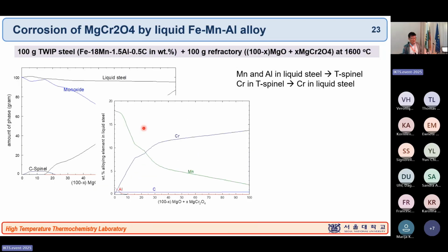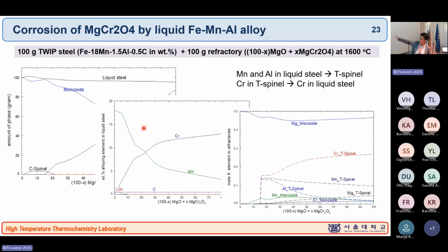But if you look inside the liquid metal, you can see a huge amount of chromium pickup, and this is coming from the MgCr2O4, of course, and then a huge decrease of the manganese, and zero amount of aluminum, because MgAl2O4 is more stable than MgCr2O4 from the Gibbs energy point of view. And also MnCr2O4 can be one of the stable phases. That's because of this interaction reaction happening. Eventually you can see that your refractory, for example MgCr2O4, can change its composition because of this chemical reaction, so you see huge degradation of this kind of refractory. Of course, if you are using MgAl2O4, it's very stable, very good, and you can prove that by the thermodynamic calculation.